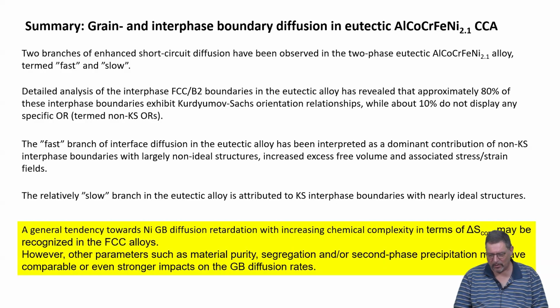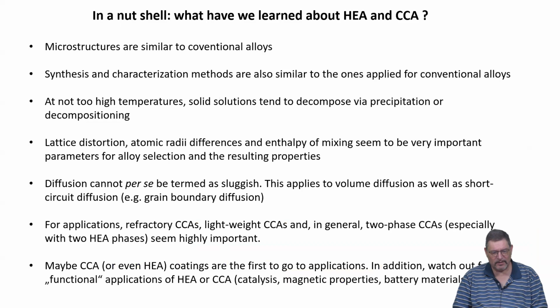And again, there is no tendency in a generic form that would relate configurational entropy, high entropy behavior, to how transport along an interface or a grain boundary would work out in the end. So what have we learned about high entropy alloys and compositionally complex alloys? I would say microstructures are rather similar to what you find in normal alloys. I didn't see any paper in the literature which reported anything which we haven't seen before. But that doesn't mean these high entropy alloys are bad or boring, right?